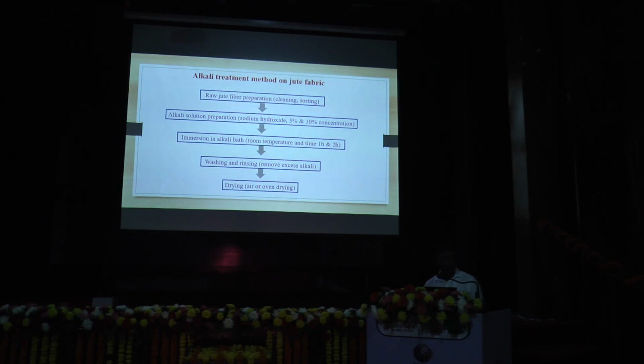Then this is the method of alkali treatment to the jute fabric. First the raw jute fabric is prepared, first cleaned, then sorted. Then alkali solution is prepared using 5% and 10% solution concentration. Then immerse in the alkali bath at room temperature for 1 hour and 2 hours. Then washing and rinsing to remove excess alkalis, and then drying, air or oven dry.